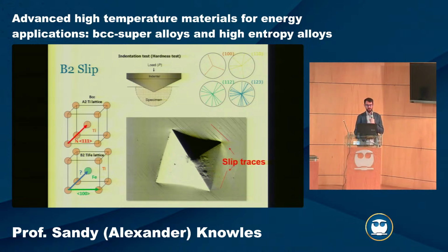One of the challenges is that in the titanium iron intermetallic and some of these other intermetallics, rather than having slip to this body centering position, when you do that, you swap the two atom types. So you have your A atom on one corner and the B atom in the middle. If you imagine a dislocation that goes through that corner, along the diagonal, it's going to swap the atom positions. And so that creates an antiphase boundary, and that has an energy penalty to it.